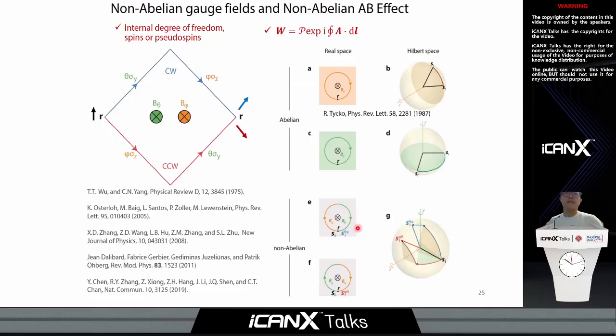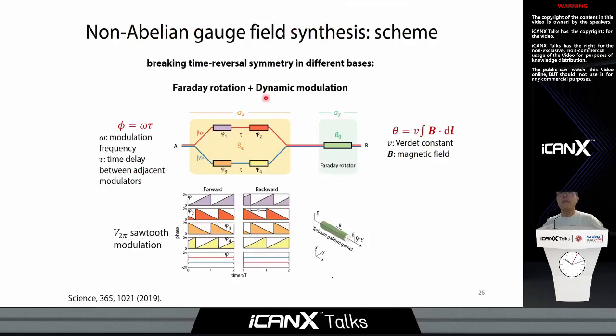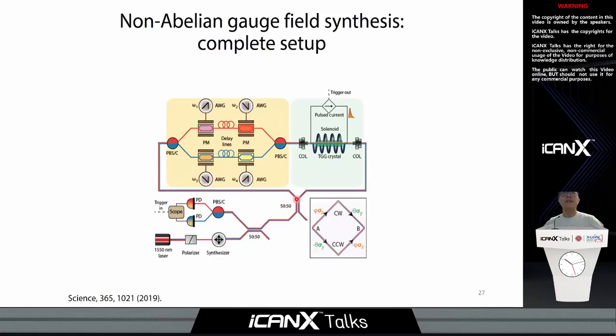We realize these non-abelian gauge fields by breaking time reversal symmetry in different bases. The first one is the Faraday rotation, as is well known, and the second one is dynamic modulation using lithium niobate modulators. We do this by modulating the lithium niobate with sawtooth modulation at V2pi, which gives us an effective sigma z degree of freedom for the non-abelian gauge field. In the full setup, we combine the two ends, point A and B, into an interferometer, and we read out their interference by doing a projection detection.